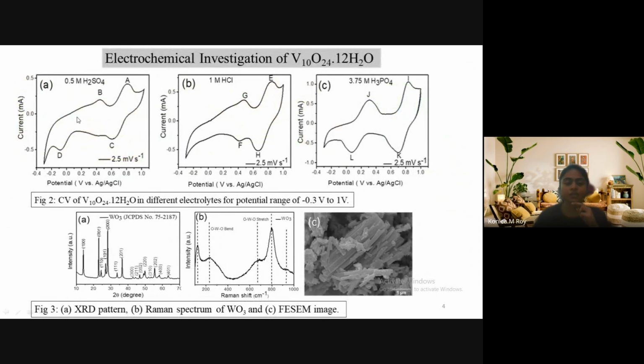For the electrochemical investigation, we did the CV in 3 different electrolytes, taking the same proton concentration: 0.5 molar of H2SO4, 1 molar of HCl, and 3.75 molar of H3PO4. And this is the CV profile. Here it is showing the redox activity, with reduction in the discharge mode. And this one is the charging mode, where anodic peaks show that the protons are coming out of the electrode material. In the 3 electrolytes, it shows the same kind of behavior, running on the more positive side potential from minus 0.3 to 1. So we have chosen this one as the cathode material.